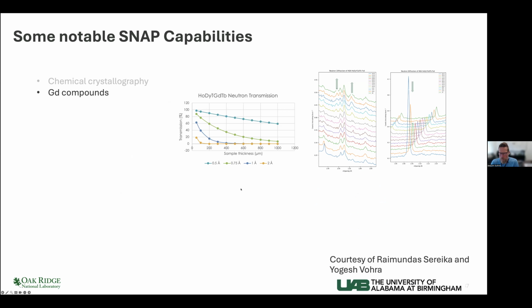This is some work from Yogesh Vohra's group, looking at gadolinium compounds. For those who don't know, gadolinium is a massive, massive neutron absorber. So this shows a transmission as a function of sample thickness. Essentially, if your sample is more than 100 microns thick, you don't see it anymore. Yet on SNAP, we are able to see these nice diffraction patterns because we are so well optimized for looking at small samples. Well, small, in the case of neutrons, this is a very, very microscopic sample. It's probably still large for synchrotrons, but when you get down to 100 micron levels, that's still impressive, at least for neutrons.